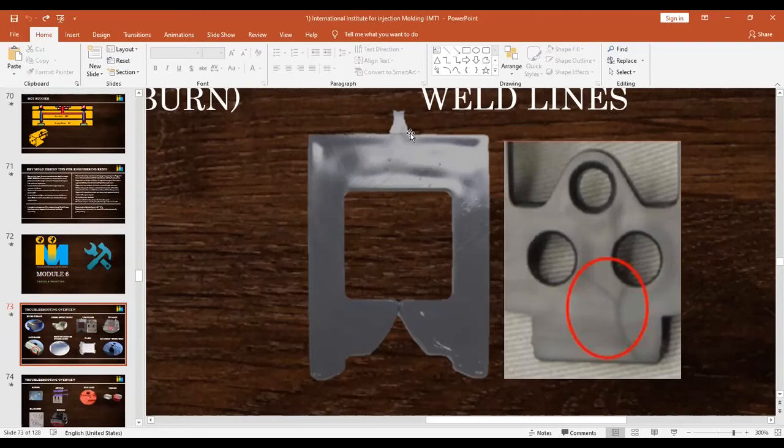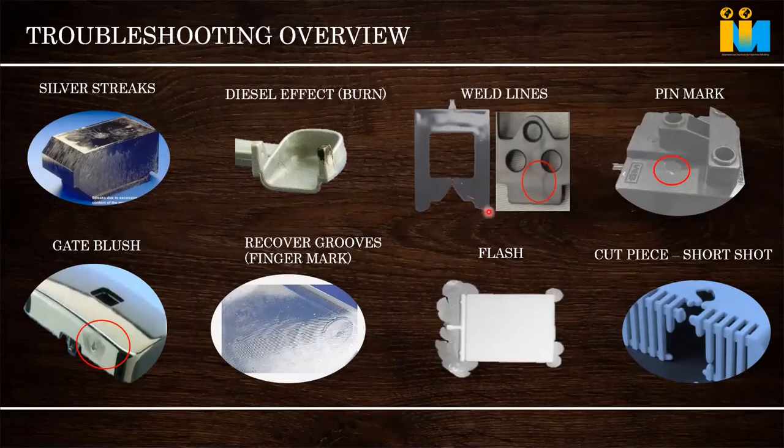So there will be a reduction in the mechanical property. You can see a line on the part. Sometimes if you bend the part, it can break also. How to optimize the weld line? You can see there is an angle here. Normally if the flows meet head on, like at 90 degrees, then the weld line will be very severe. If it has a bigger angle, above 135 degrees instead of 90, it becomes a meld line. A meld line is better in strength than a weld line.